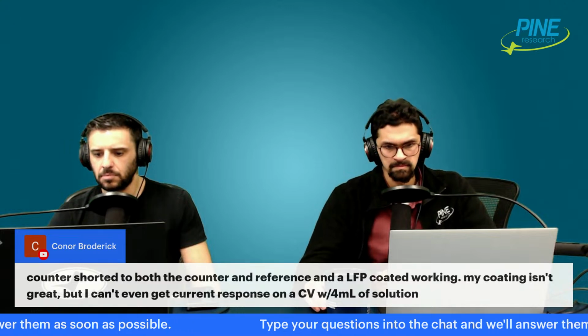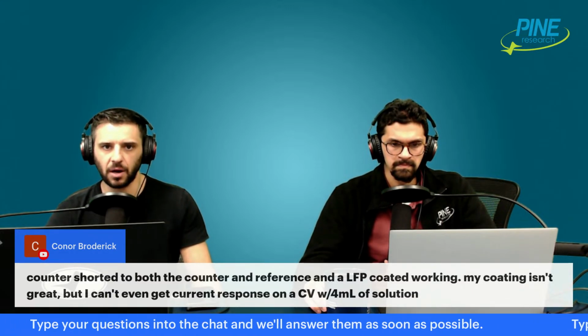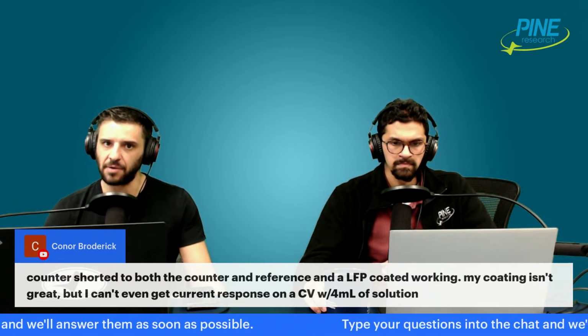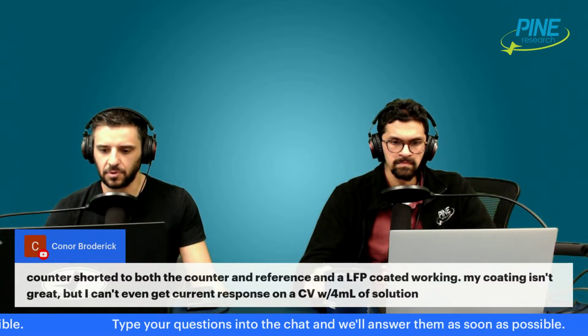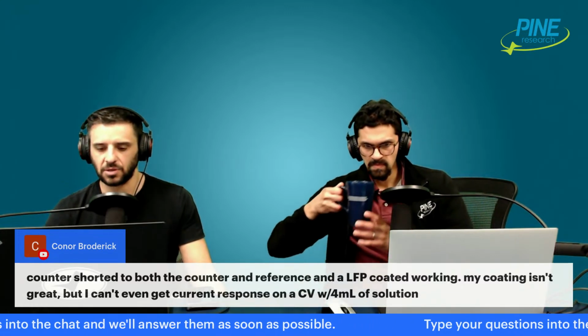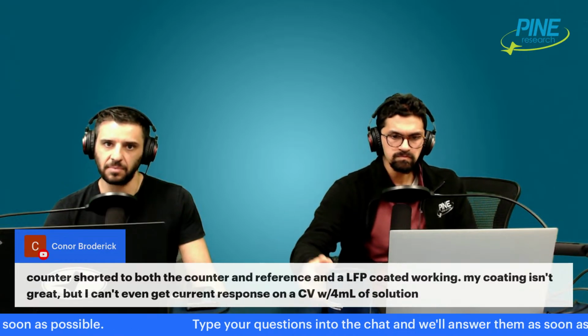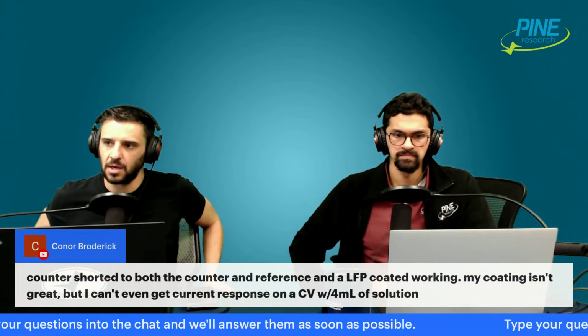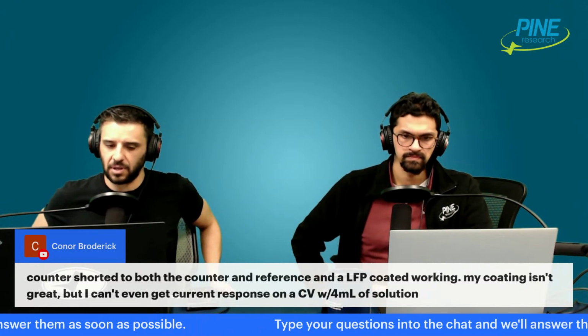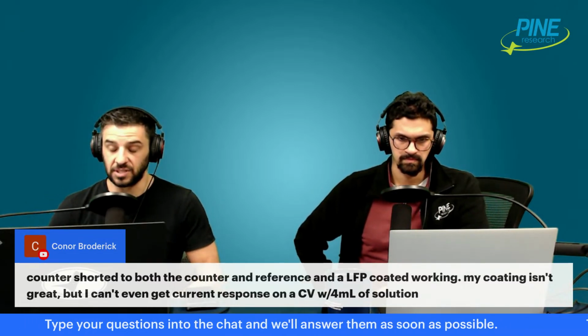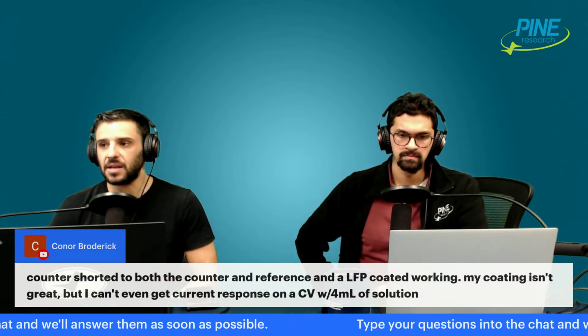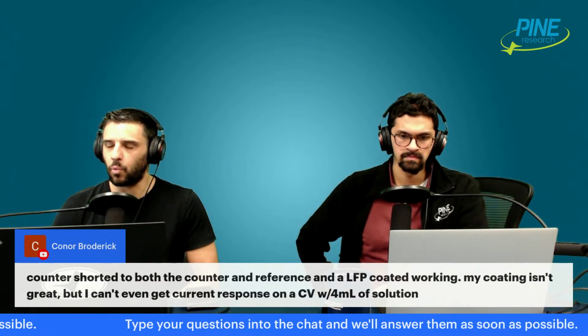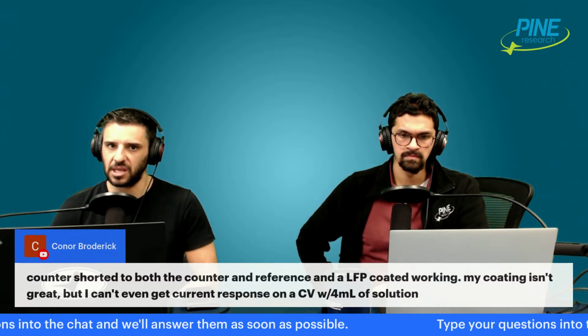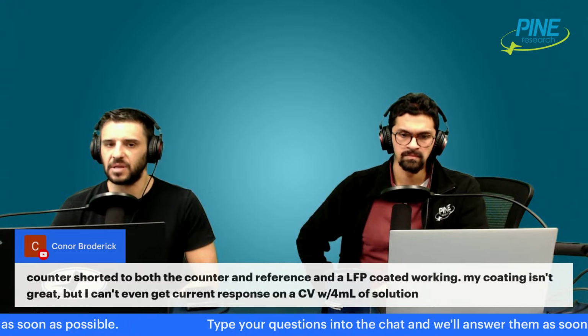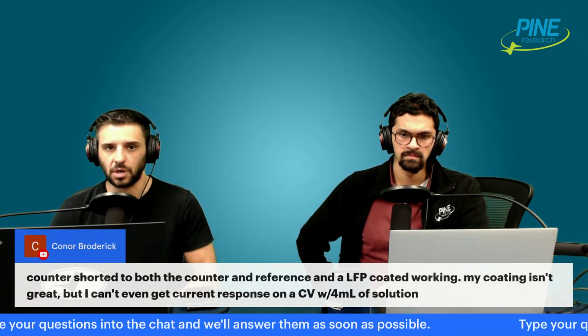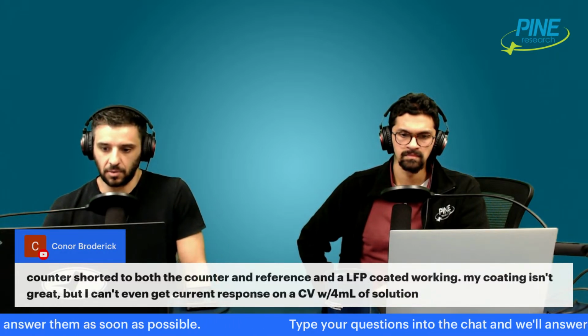Okay. So the main concept here to be aware of with battery electrodes, battery materials, and thinking through part of what Alex just said about the distance between the reference and the working electrode adding to uncompensated resistance: first of all, with battery materials, even with relatively concentrated electrolyte, the resistance is higher. The solvents you're using for battery electrodes have higher resistance than water and stuff like that. The second is that I don't know how well I can describe why theoretically, but battery electrodes require proximity and pressure. If you are trying to do 3 electrode experiments with lithium salts and lithium batteries, you will struggle heavily, as you seem to be mentioning as part of your questions.